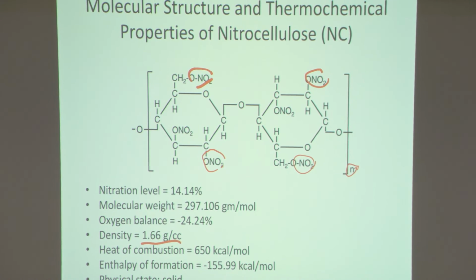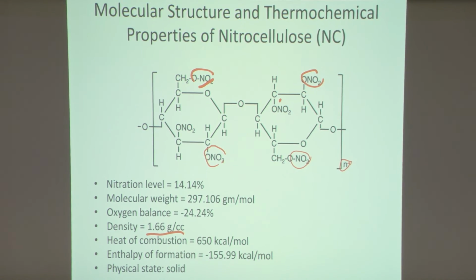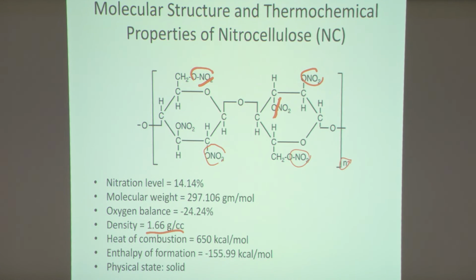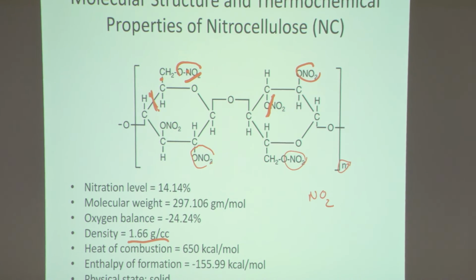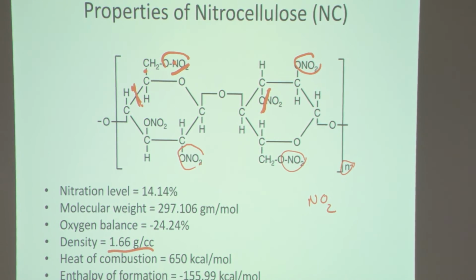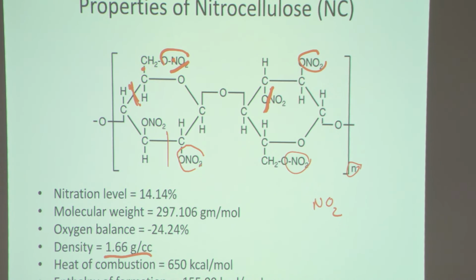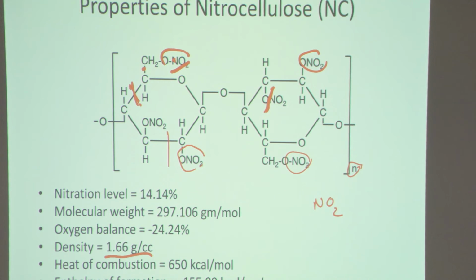react? Well, if you start looking at the weak bonds, they are going to be the O-NO2 bonds. So as I thermally heat it up, I'm going to break that O-N bond. And off of it, then I'm going to get NO2. And then what's the next weakest bond after I remove that? It's basically a one-removed bond that typically becomes the next weakest. So if I look at something like this, this bond breaks, okay, here's one. So the next bond that might break is this one removed. And once I do that, I open up the ring and I continually open it up, and eventually I form a lot of formaldehyde plus other aldehydes. And that NO2 then reacts with the formaldehyde and the aldehydes in the gas phase.